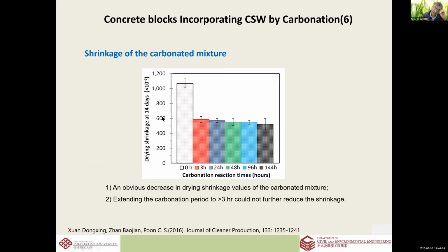So not only does it have good strength and use waste material, it can also reduce the shrinkage, because shrinkage is caused by the dehydration of CSH. But some of the CSH is converted to carbonate, and so the shrinkage is much reduced.